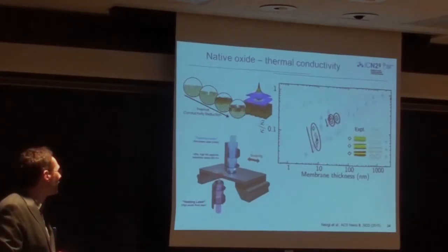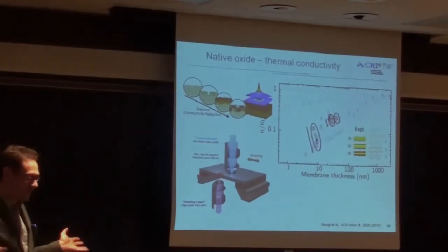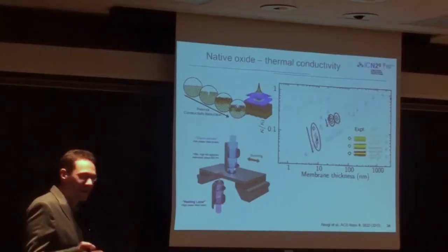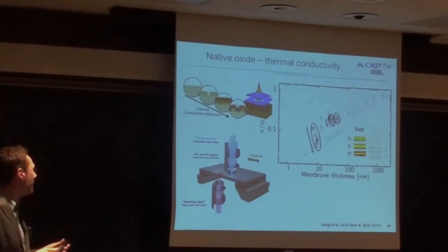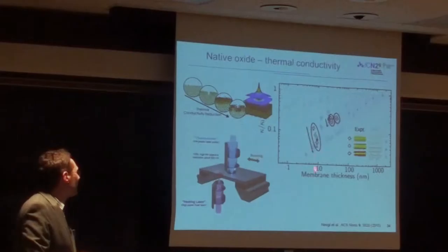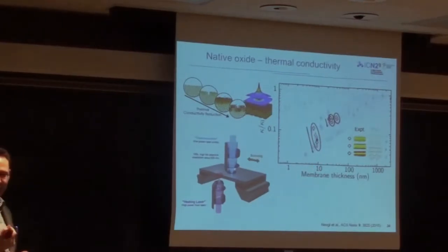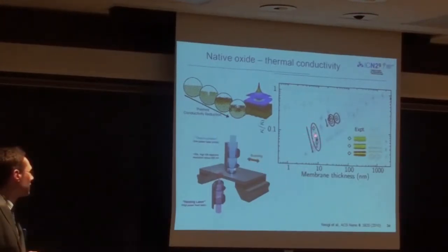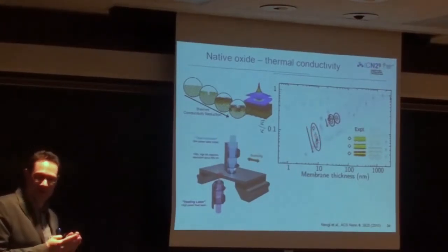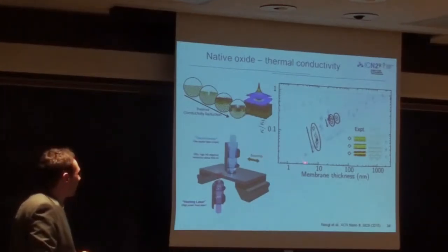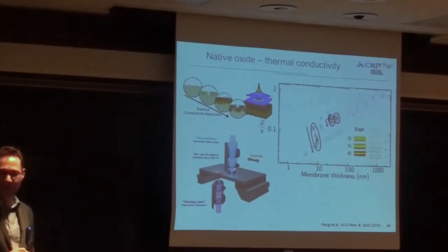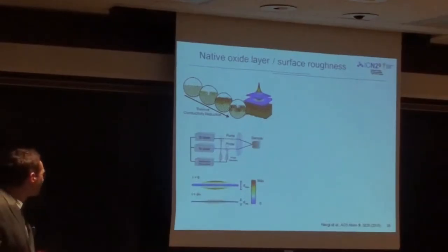Well, of course, if you consider thermal phonons, let's just put a number, let's say a terahertz, of course, there is a widespread distribution, but for a terahertz, for silicon, the phonon wavelengths would be in the range of 8 to 10 nanometers. So basically this effect becomes very pronounced when the wavelength of the thermal phonons is of a similar dimension as the dimensionality of your material.